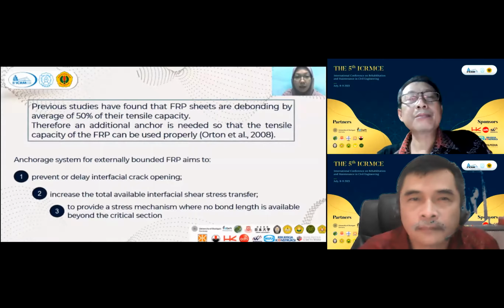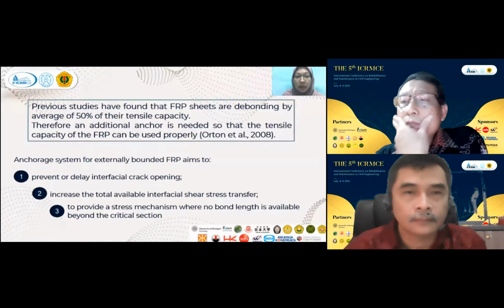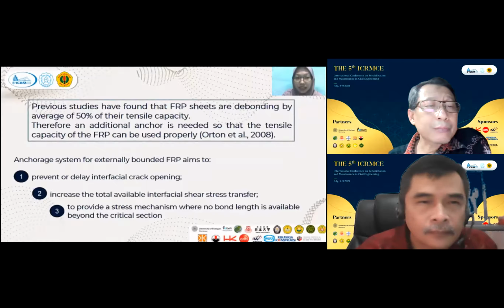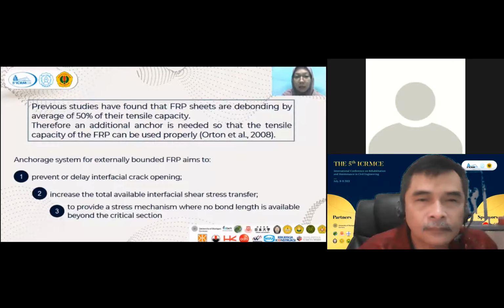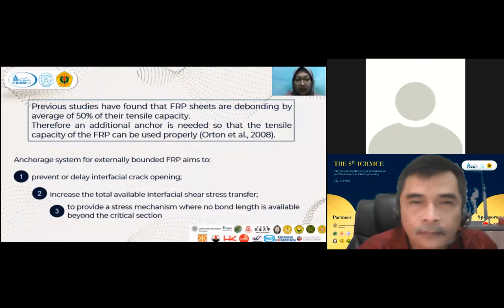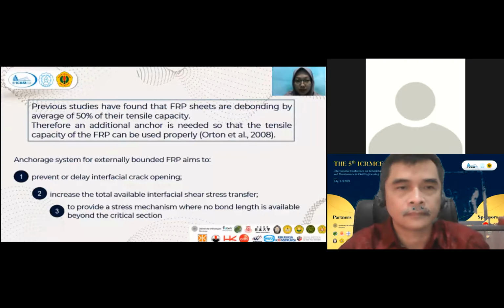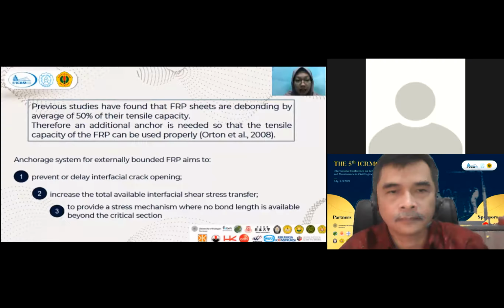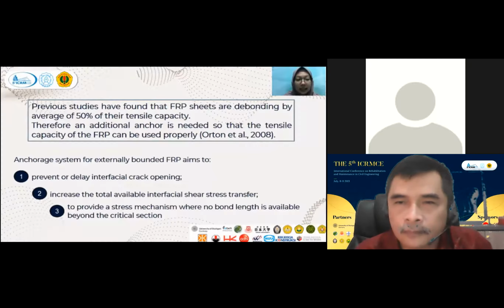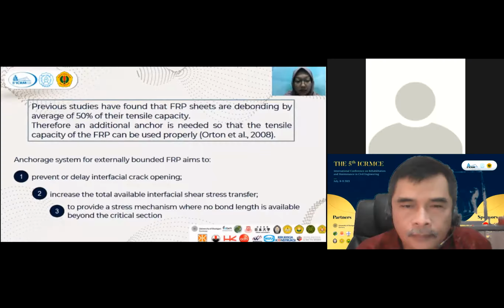Previous studies have found that FRP sheets debond at an average of 50% of their tensile capacity. Therefore, an additional anchor is needed so that the tensile capacity of the FRP can be used properly. Anchored systems for externally bonded FRP aim, first, to prevent or delay interfacial crack opening. Second, to increase the total available interfacial shear stress transfer. And the last one, to provide a stress transfer mechanism where no bond length is available beyond the critical section.